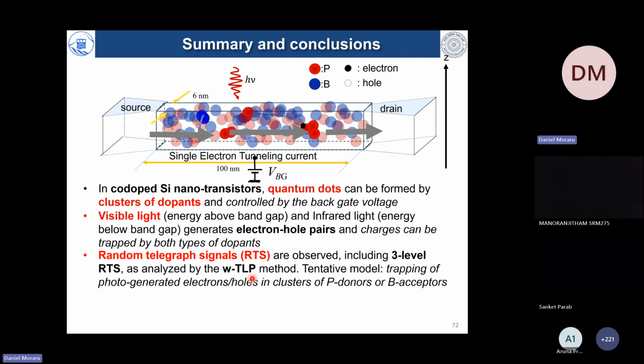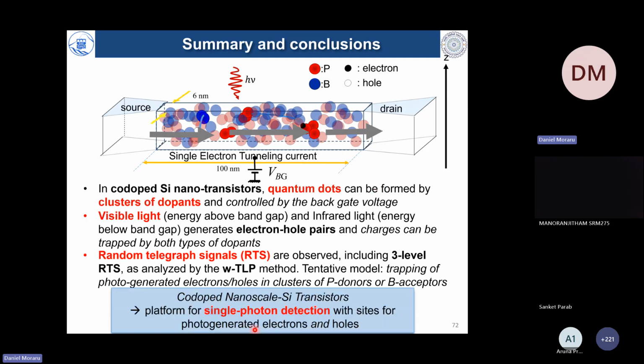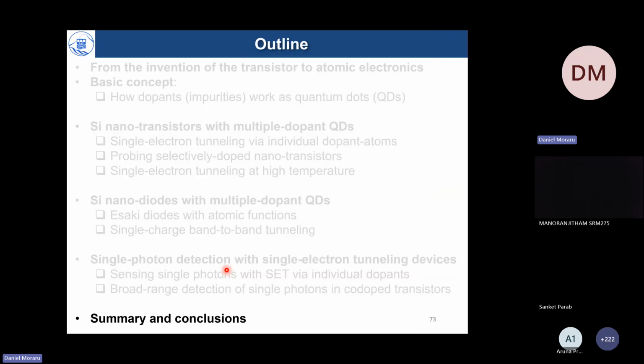On the other hand, we can use the random telegraph signal analysis with WTLP, and finally, we demonstrated that infrared sub-band gap irradiation of phosphorus can actually be detected. And the reason for this is that the clusters introduce very deep states, and those band tail states actually mediate the electron and hole capture effects. So what I'm trying to demonstrate here is that co-doped nanoscale silicon transistors can be a good platform for single photon detection, and hopefully we can explore this in the future a little bit more.